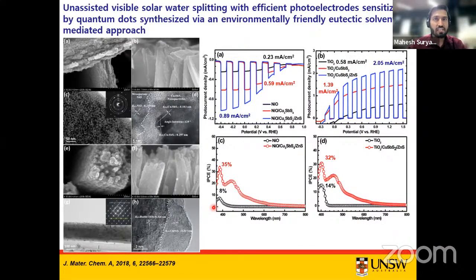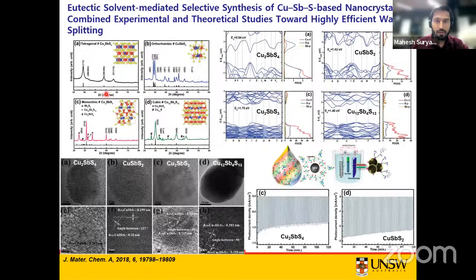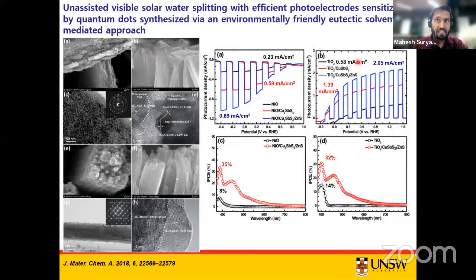So after careful analysis of these compounds, what we have done is we employed ultraviolet photoelectron spectroscopy to find out the band alignment of this Cu3SbS4 and the CuSbS2 material, and then we designed an unassisted system. What we found out using these ultraviolet photoelectron spectroscopy studies is that the Cu3SbS4 material is a good sensitizer to load on the NiO nanosheets, which will act as a photocathode, whereas CuSbS2 is a suitable sensitizer for TiO2 nanorods, which will act as a photoanode.